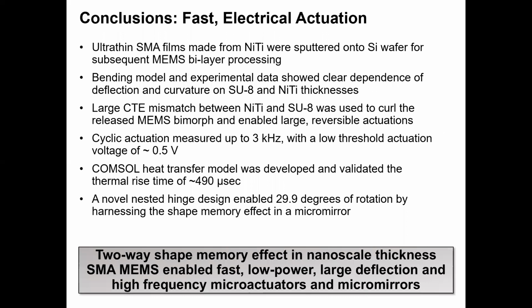So in conclusion, the final significant contribution of this dissertation has shown that two-way shape memory effects in nanoscale thickness SMA MEMS have sufficiently enabled some scientific and technical advancements related to low power, large deflection, and high frequency microactuators and micromirrors for a variety of applications relevant to defense and commercial industries. So overall, this effort progressed from the early stages, which focused on ensuring crystallization in nanoscale thickness SMA films based on this nitinol alloy, which enabled the design and fabrication of fast actuators with tailored curvature, and ultimately led to a first ever demonstration of an SMA micromirror array with micrometer sized pixels.